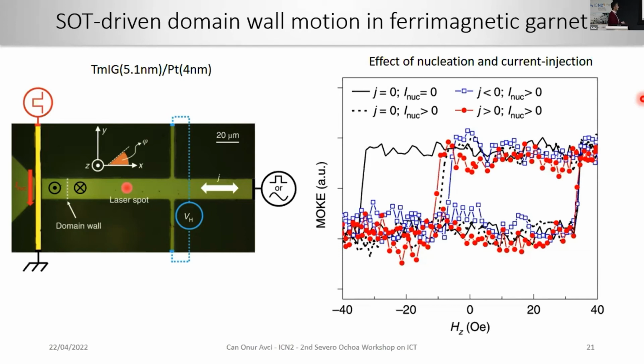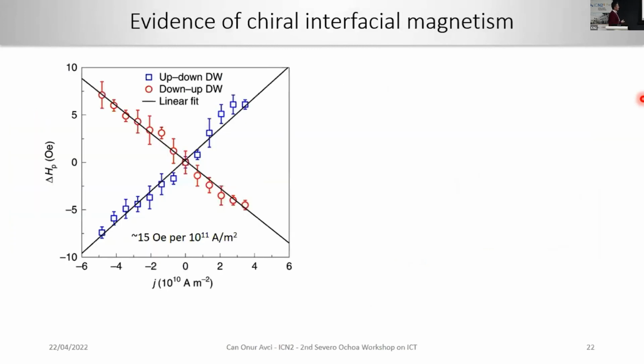We tested this hypothesis, and we indeed found evidence that this current can have an influence on the domain wall here, as exemplified in this data. And the effect that the current creates on the domain wall actually scales linearly with current. That further reinforces the hypothesis that we have some torques acting on the domain walls.